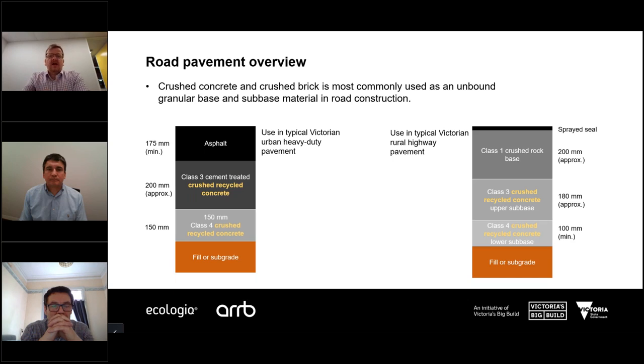If we have a look at the pavement on the right-hand side, that represents a typical rural highway pavement away from the metropolitan areas. And that, instead of having an asphalt surface, has a sprayed seal surface, and the remainder of the pavement structure is unbound granular material. The base material is a crushed rock base. It could potentially be a crushed recycled concrete base, but only in a lightly trafficked road, which wouldn't be a rural highway. But in heavily trafficked roads like our rural highways, that recycled concrete can't be used in that environment due to cracking concerns. However, it can certainly be used in the upper sub-base and the lowest sub-base as a direct substitute for virgin aggregate. And you can see that's typically 300 odd millimetres of thickness plus of the pavement. So the bulk of the pavement thickness can actually be crushed recycled concrete.